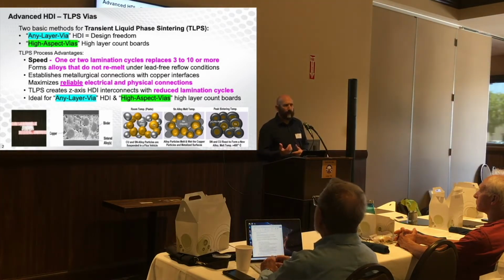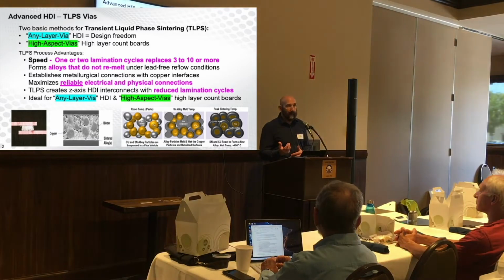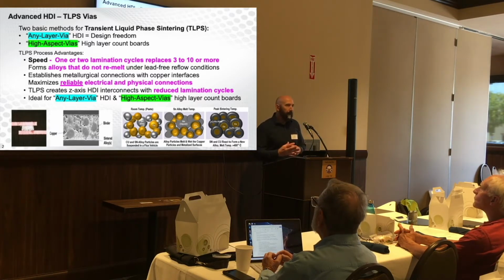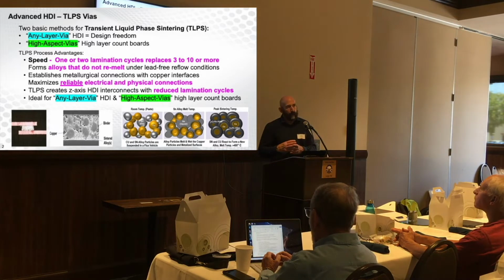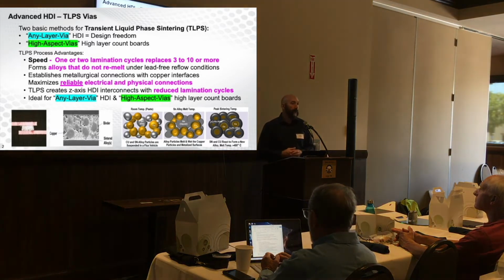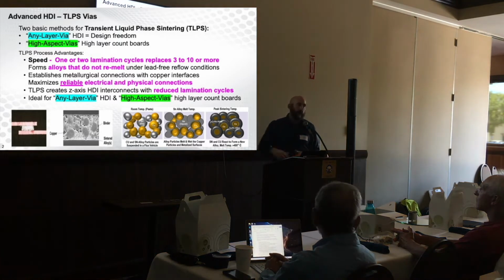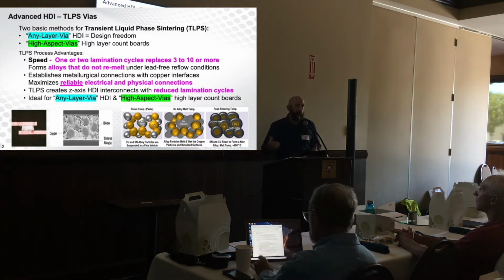I don't know if anyone's ever heard of the ALIVH process that used the copper paste. That had a binder system, and the binder system would allow the copper particles to stick together, but with any change in expansion from different temperatures, you'd have a change in resistance. Whereas this alloys with the interlayer copper and forms a metallurgical bond. It's kind of like sweating a copper pipe together. It forms that metallurgical bond.